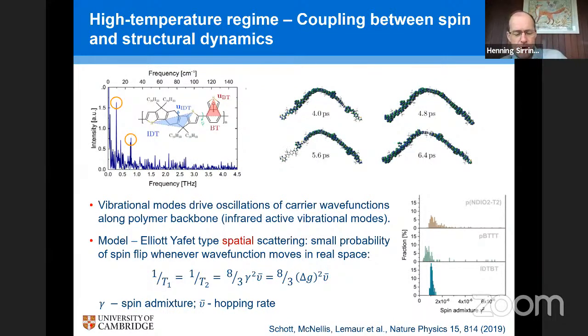This surfing motion of the charge carriers on the waves of molecular lattice distortion is relevant for the molecular systems. And in the polymeric system, something similar happens. These torsional vibrations of the backbone drive the carrier wave functions to oscillate periodically along the polymer backbone. And kind of locally, the structural vibrations drive an oscillation of the carrier wave function. And we think that this rapid oscillation of the wave functions is responsible for the spin relaxation.